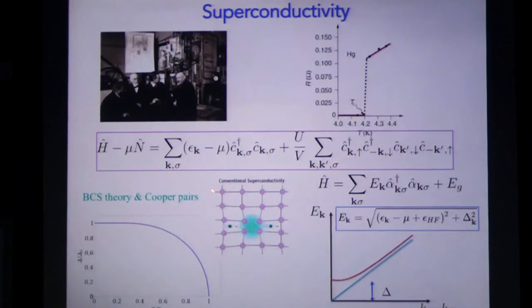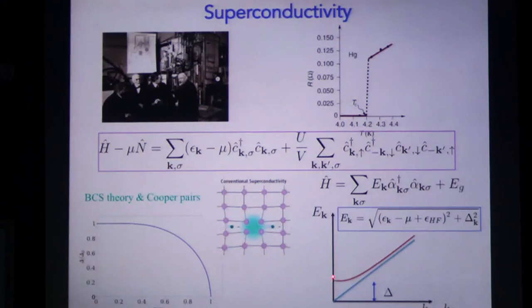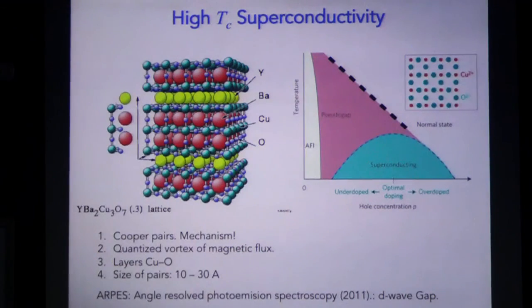The other important thing is that with the Cooper work, doing a variational analysis, this is one of the forms in which one can obtain the quasi-particle energy spectrum and see that instead of the usual parabola, what they have is a shifted parabola, which is this energy spectrum, and this energy spectrum corresponds precisely to the energy spectrum of quasi-particles paired with this mechanism associated to the presence of the lattice. This is in pink. Then, what else? But this was superconductivity, and it was understood by the Bardeen, Cooper, and Schrieffer theory.